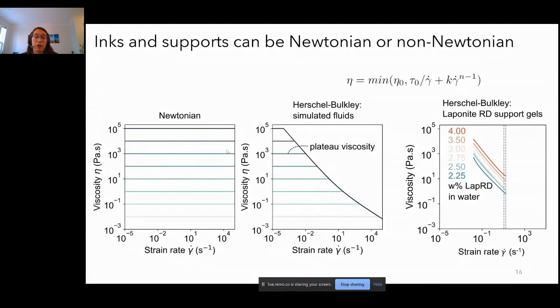We also simulated Herschel-Bulkley fluids. So these are the fluids that are like the fluids that I talked about in the beginning, where they're going to behave like a solid up until a yield stress, at which point they're going to behave like a shear thinning liquid. So for these simulated fluids, all of the behavior in the shear thinning region is going to be the same. These are all going to have the same viscosity above yield. But below yield, they have different viscosities, which I call the plateau viscosity. So that is going to extract just the effect of what the unyielded properties of the materials do to the structure of the filament.